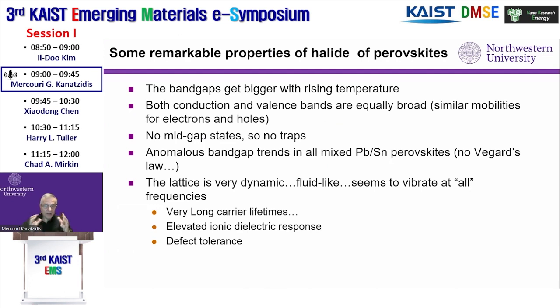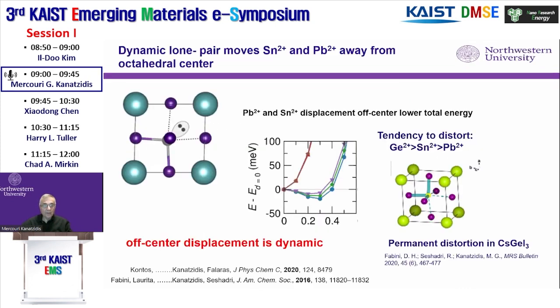The lattice of the structure is very dynamic, and in fact sometimes disordered. In some ways it's disordered and fluid-like. It seems to vibrate at all frequencies, and that is, I think, also important. This doesn't sound like a very good property, but actually it is, and it gives rise to rather long carrier lifetimes, elevated ionic dielectric responses, and defect tolerance.